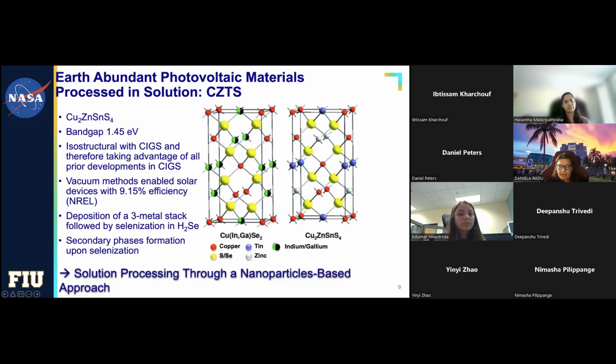Well, when we do that, when we get indium and gallium replaced by zinc and tin, we observe from the crystalline perspective, the crystallinity of the material, it's isostructural, in other words, exactly the same structure material. Wow, that's amazing. Honestly, it's like you look at your car. If you see another car, you would assume that it will work in the same way. And that was big news, like having this isostructurality would imply automatically that things will go in the same direction, okay?